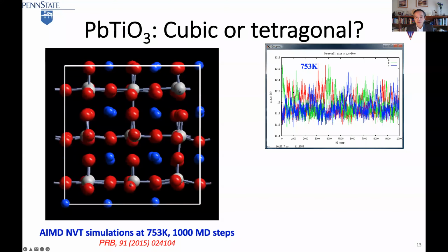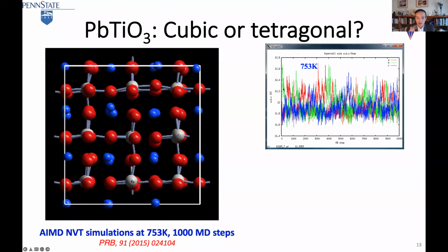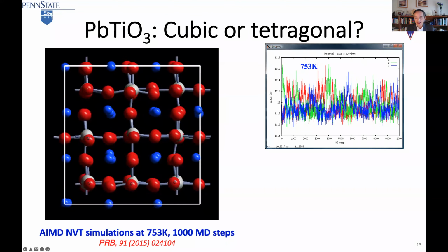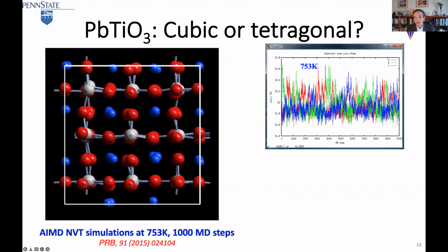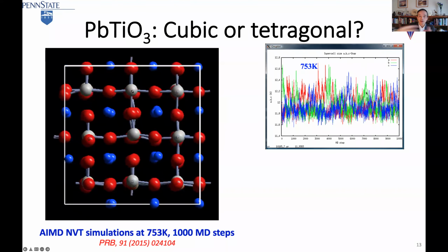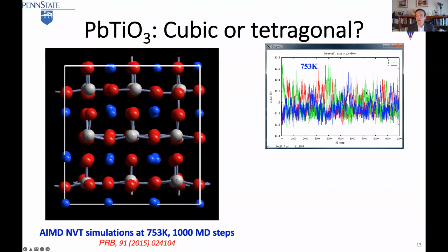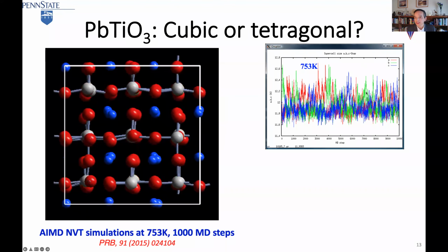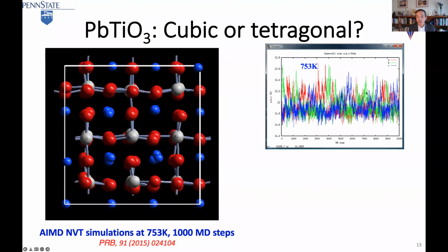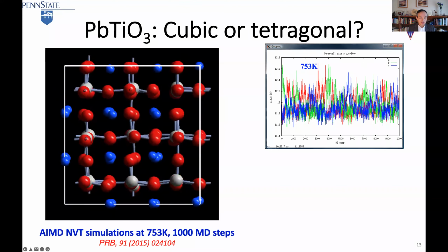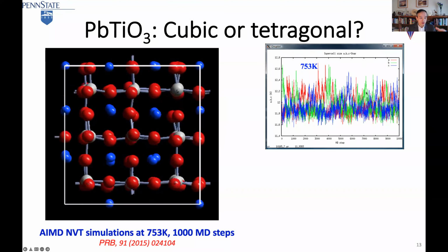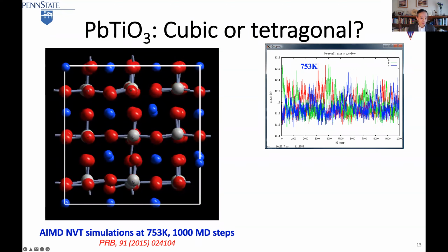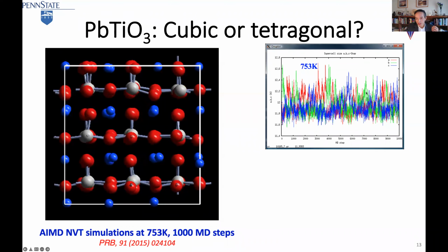So in the Z direction it's C, then A, C, A, C, A, C, right? It changes direction. Of course, A could be X, could be Y, so it's the same. So now you see it's locally tetragonal, but it switches. Of course, during the switch, you get a cubic structure, because you have to go through the middle and go to the other direction.